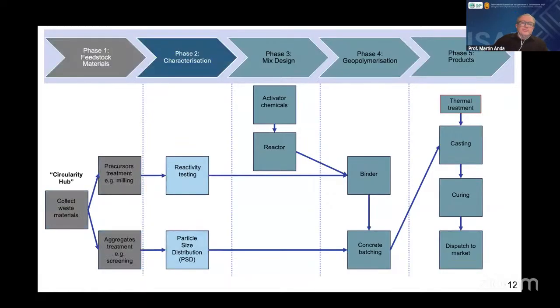In phase 2, we need to characterize these waste materials, and there's a whole raft of tests that we would do to determine the reactivity of the material. In other words, we're particularly looking for how much of the aluminosilicates in these industrial wastes are in the amorphous phase, and then we can determine a mix design from that. In other words, what type of activated chemicals we need to add. But if these wastes are going to be the aggregates, well, then we might need to do a range of testing on them, such as particle size distribution and compressive strength and so on.